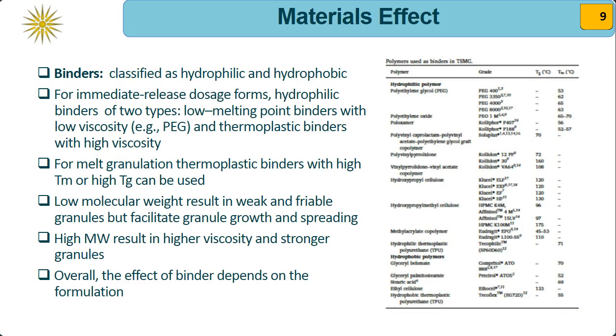As we mentioned, the processing parameters are very important for the quality of the produced granules. However, there's an important effect of the materials that we use to form the granules. The binders, which are usually classified as hydrophilic and hydrophobic, have a strong effect on the produced granules. For immediate release dosage forms, we use hydrophilic binders, which are usually of two types: the low melting point binders with low viscosity, such as polyethylene glycol, or thermoplastic binders with high viscosity. For melt granulation, we can use thermoplastic binders with high melting points or higher glass transitions, and usually low molecular weight results in weak and friable granules. But it has been found that it facilitates granule growth and spreading. High molecular weight of binders results in higher viscosity and, of course, stronger granules.